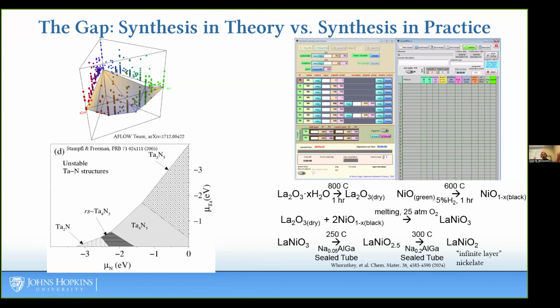Or in other cases, here's a pure solid state one. It's not a single step, right? First I have to clean up my starting reagents. This is to make an infinite-layer nickelate, which is a thin film superconductor. You have to clean up your reagents to begin with. You then have to make the material, and you need high pressure oxygen to do it. And then you have to remove the oxygen, and to do that you need a two-step process or one-step process, depending on how you do it. But the point is, it's now a multi-step process.